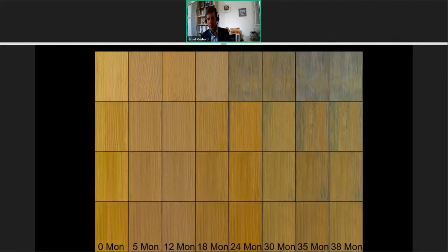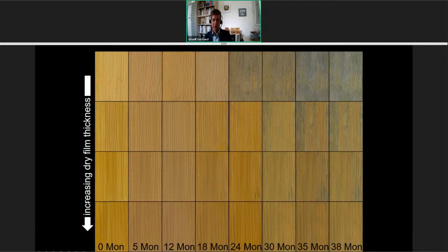If we now look at a series of weathering samples over 38 months of natural weathering, you see different rates of degradation. The first one degrades very quickly, so that after 24 months of natural weathering, you see really gray surfaces and heavy flaking of the coating system, whereas the last one is still in quite good shape at month 38. The secret is that this is the same coating system with increasing dry film thickness. So this is low film thickness of the same coating system up here and high film thickness here.